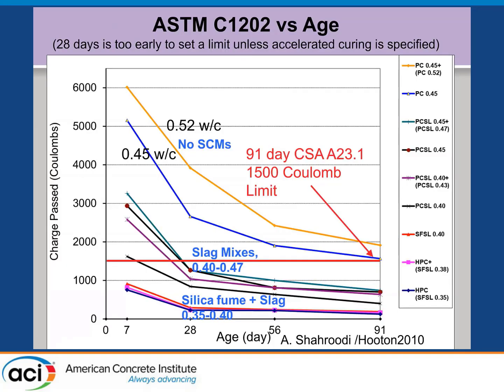And just to show the sort of change that can occur, you get big reductions in time at 7, 28, 56, 91 days. We set our limit, the one I just mentioned, at 91 days. So Portland cement concretes on their own probably won't make it or will be just on the edge. Whereas the slag mixes, these are all slag mixes here, these next four, they all make it handily. In fact, they would make it at 56 days.